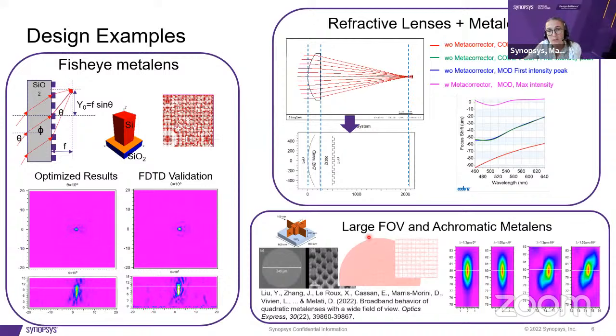Then we can also talk about large field of view and achromatic Metalenz. It was already mentioned earlier by some other speaker how challenging it was in terms of efficiency, and indeed it is a really challenging design. On our side, we were using this type of meta-atoms library of rectangular shape. It's coming from an idea from the University of Paris. Now having this meta-atoms library, we generated the Metalenz surface in order to have, for 1.3 micrometers and 1550 nanometers, an equivalent focal distance for different angles of incidence. Here it's at 0 degrees and at 40 degrees. And again, it's by adding some optimization targets inside the design case.